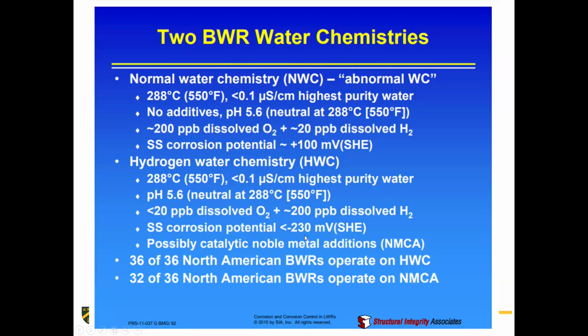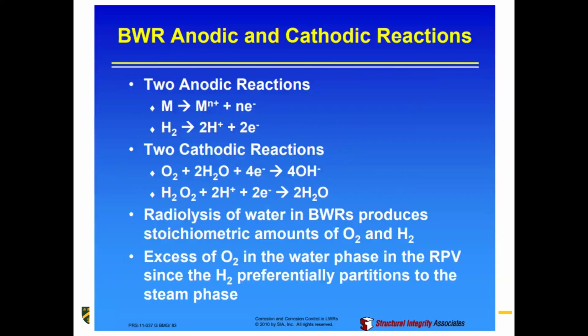So kind of similar to when I was talking to you before about pitting, and pitting has a particular potential for initiation. This intergranular corrosion is similar in that sense, where if we're controlling our electrochemical potential, we can drop it low enough with good chemistry to prevent this from happening in the first place. So this caught on very, very well. Every North American BWR, as of this lecture, which is a 2010 lecture, every single one was operating under this hydrogen water chemistry. And a whole bunch of them were operating under a regime that we'll talk about in a little bit. But I don't want to get into what that acronym, the NMCA, means yet, because that comes later in the lecture. So very, very successful, essentially universally applied.